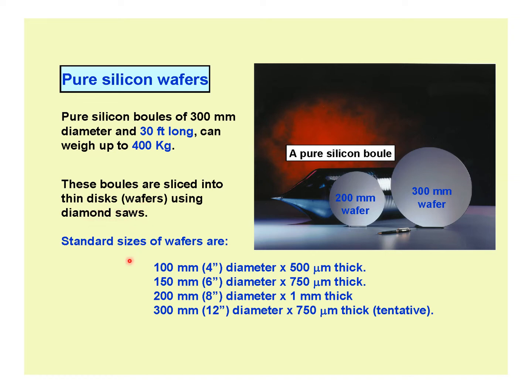The standard sizes of wafers available for MEMS fabrication are: 4 inch at 500 micrometers thick, 6 inch at 750 micrometers thick, 8 inch at 1 mm thick, and 12 inch at 750 micrometers thick.